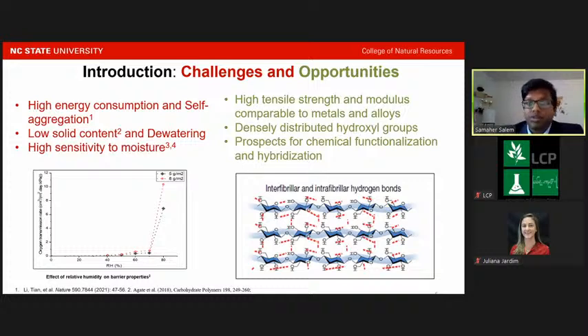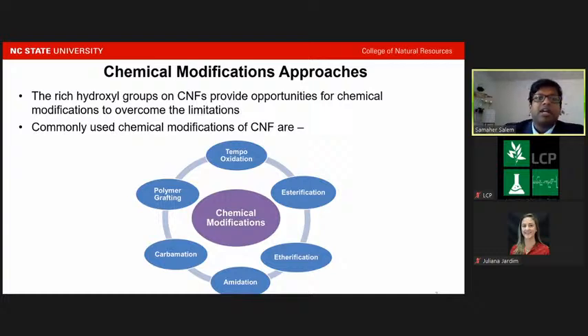High tensile strength, modulus comparable to metal and alloy, densely distributed hydroxyl groups, which are critical for forming abundant inter- and intramolecular hydrogen bonds, and prospects for chemical functionalization and hybridization. The rich hydroxyl groups on CNF provide opportunities for chemical modification to overcome the limitations. Commonly used chemical modifications of CNF are TEMPO oxidation, esterification, etherification, amidation, carbamation, polymer grafting, and so on. However, in my work, I have used esterification.